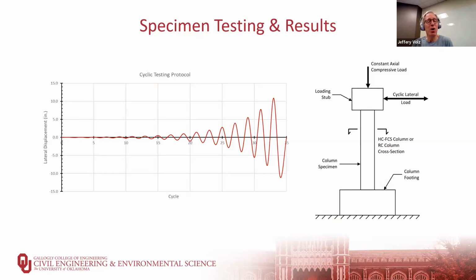And that loading protocol is you start with an initial displacement. You push the column in one direction for that displacement. This is all a displacement controlled test as opposed to a load controlled test. So you displace it by that amount. You pull it back to 0, and then you pull it in the other direction, the same amount, push it back to 0, and then do a second cycle at that same displacement. Then the next cycle is done at a 40% higher displacement. 2 cycles of that, 40% increase, 40% increase. So the displacements are increasing exponentially, and that's shown in the diagram on the left.